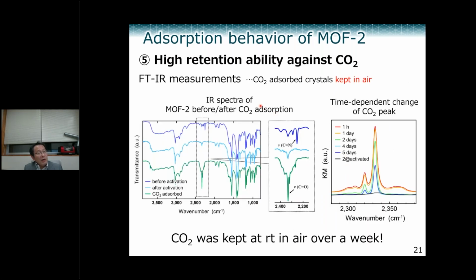Then we investigated this behavior using FTIR. Using the vibration spectrum, we monitored this phenomenon. First, before removal of acetonitrile, this is the IR spectrum. You can see the acetonitrile CN triple bond stretching band here. After removal of acetonitrile, this band disappears. So we should pay attention only to this range now. After introducing CO₂, we can clearly see the carbon dioxide band here.